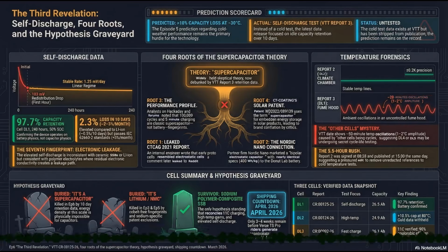We have 3 fully verified, publicly documented cells. DL1 provided the self-discharge data. It demonstrated an initial capacity between 26.5 and 26.7 amp hours and proved a 97.7% capacity retention over 10 days, killing the supercapacitor rumor. DL2 provided the extreme thermal data.